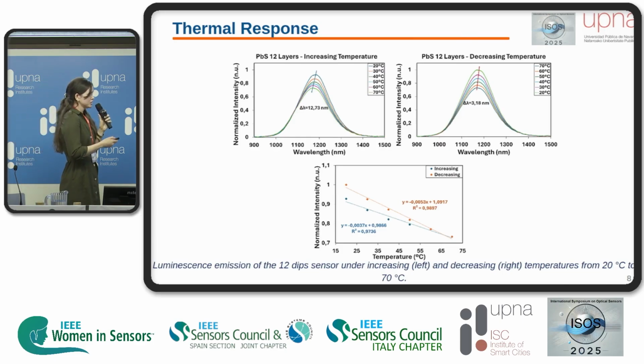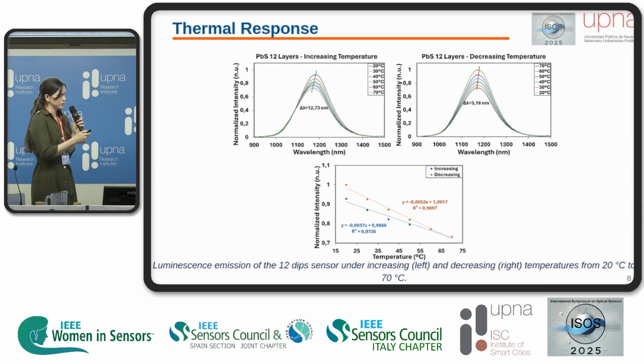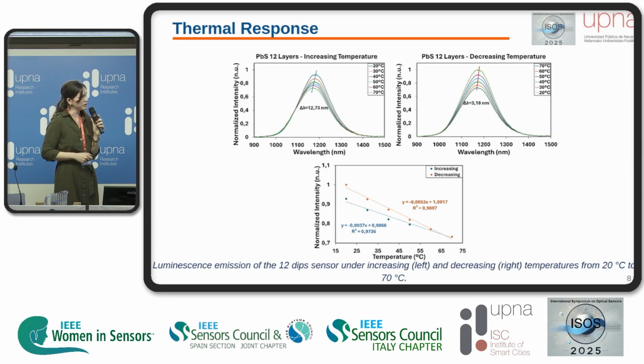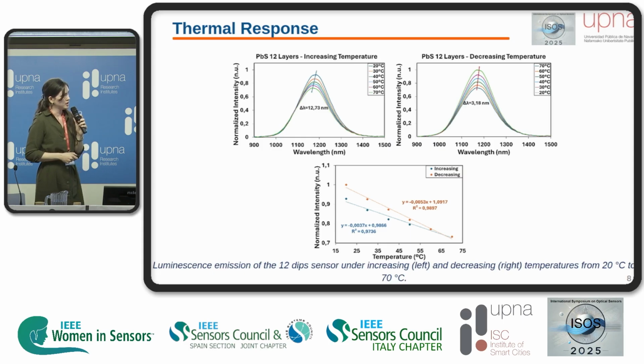Here we can see the response for the sensor with 12 dips. We can see a clear thermal quenching effect. The intensity of the emission decreases when temperature increases, and we also observe a blue shift consistent with confinement effect and interdot coupling. On the other hand, when temperature decreases, emission intensity increases, and we also observe a shift toward the near infrared. The sensor presents good linearity and a resolution of 0.8 degrees Celsius.